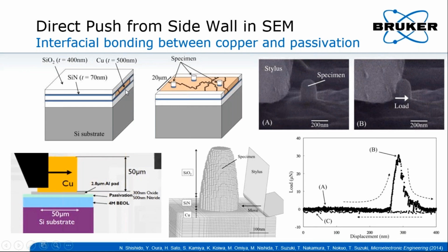The first step is using FIB to create micropillars of passivation standing on different locations of the copper surface. After that, use the probe to push the micropillars from the side wall and collect the force required to push them down. In order to turn the critical load into the adhesion work, a finite element method was established, shown here.